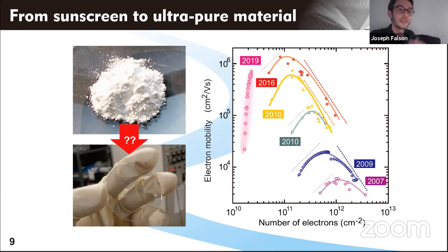Whereas oxygen is a relatively stable molecule. So we were able to reveal that by growing using ozone as opposed to oxygen radicals, which was what we were previously using, we could again reduce the amount of defects dramatically and go from the green to the yellow.